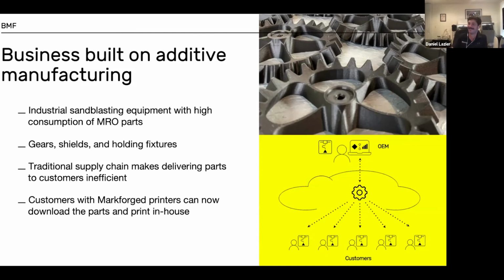Kyle asked, and I think you just answered this. What's the material that you're printing that gear with? Yeah, so in this case, I'm just actually using the onyx material, which I brushed across it, but to really pay off what that is. So it's a thermoplastic. It's a nylon 6 that has chopped carbon fibers embedded in it. So about 20% by mass, in fact, is carbon fiber itself. And that's before we start to inlay the continuous fibers.